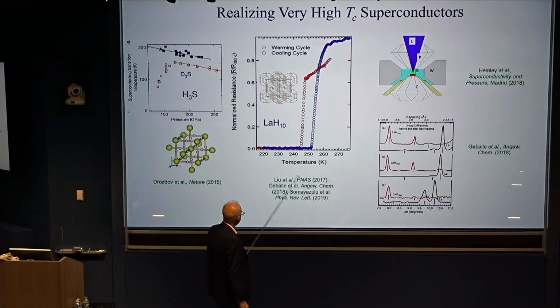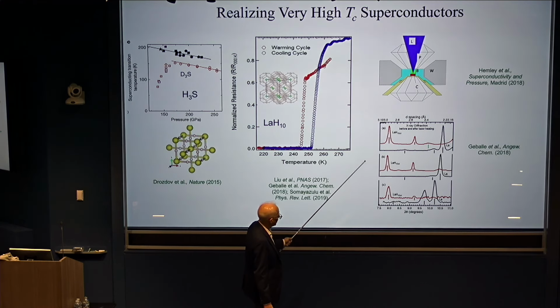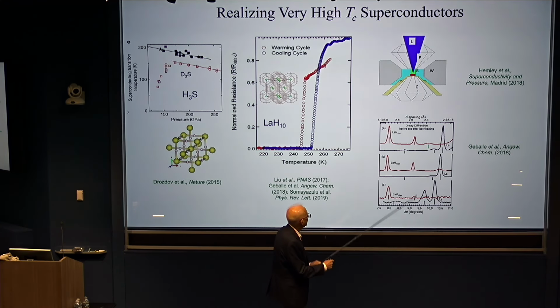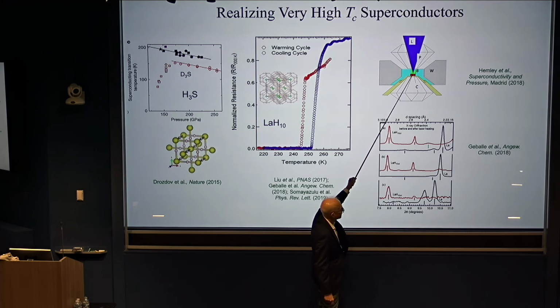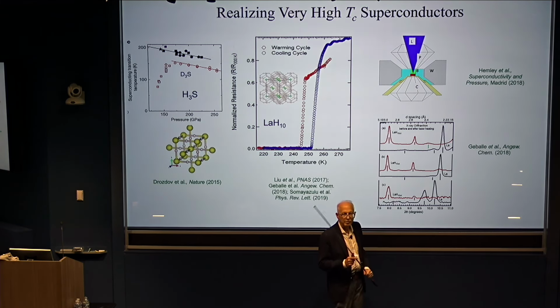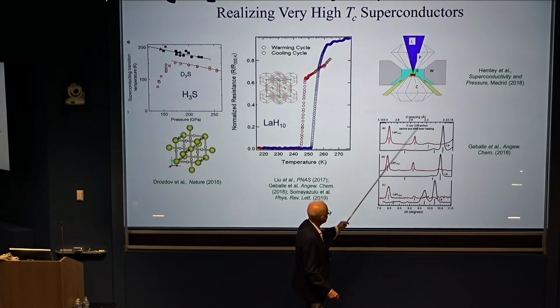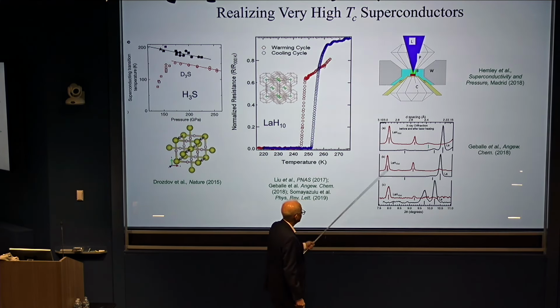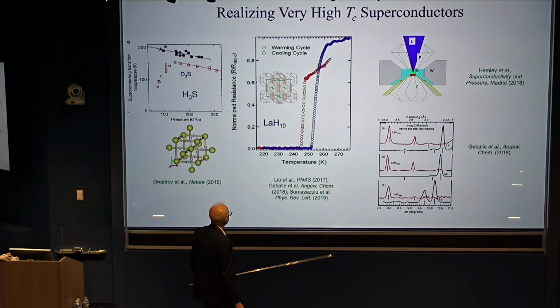We, on the other hand, decided to look at rare earth-bearing materials and the higher hydrides, and we did our own calculations and found this particular structure, lanthanum H10, mapped out the structure by X-ray diffraction, and then within a few months actually did an experiment where we could measure the superconductivity. This was actually a much more challenging experiment because we had to make the sample by laser heating the sample inside a diamond anvil cell without chemical reactions affecting the electrodes. So it was a real challenging experiment, but it was a benchmark for us and for the field.